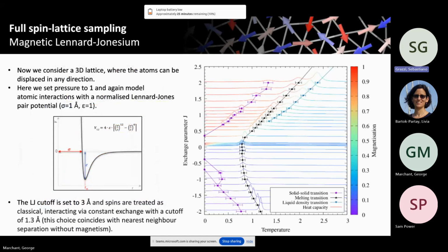And this is just more on a 3D system. It's another similar phase diagram where we can look at different structures. It's interesting as you increase the size of the exchange parameter. At some point, it starts to mix with the chemical atomic ordering transition, such that at the lower exchange parameter values, we have our structural phase transition here, and we get to a lower temperature, and you can see from the color change that the system has become ferromagnetic at some lower temperature. And these are our TCs.